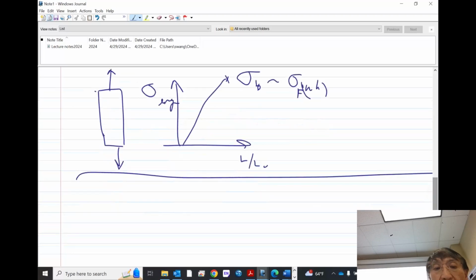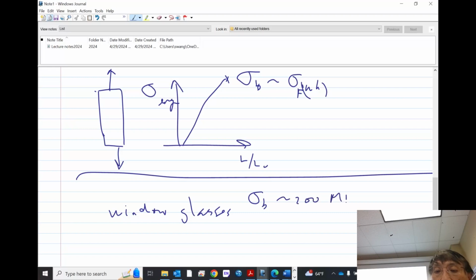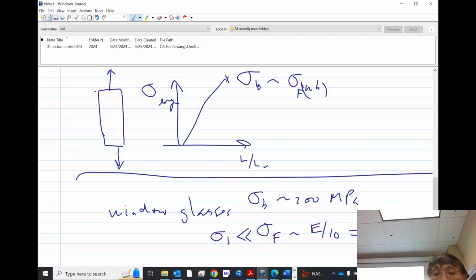I actually can mention that if you take rudimentary, let's call it window glasses. If you have window glasses, then it turns out this sigma B, let's say it's about 200 megapascals. And based on things I'm going to skip, but it's in chapter 8, people think this kind of atomic solids we can estimate its strength, meaning strength in its idealized structure. And it should be about 1/10 of the Young's modulus, which you can measure. It's very hard. It turns out 1/10 of Young's modulus is already 7 gigapascal. So it's much larger than sigma B.